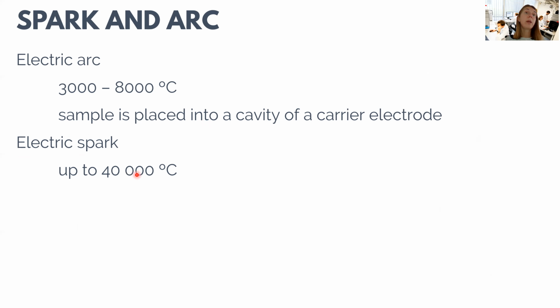Similar is electric spark, but here the temperature is extremely varying and can be up to very high, so 40,000 °C. However, the problem with both spark and arc is that the temperature depends extremely on the sample, on the length between the two electrodes, as well as other factors. So as a result, the temperature is varying very much, and the arc and spark are not so stable, and quantitative analysis is almost impossible because the reproducibility of the temperature is so poor, and as the reproducibility of the temperature is poor, also the excited to ground state ratio of the analyte is very unreproducible from experiment to experiment. And this is therefore not suitable for quantitative analysis.